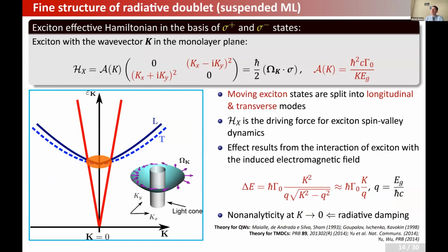So in a more formal way, you can derive this kind of expression for the effective exciton Hamiltonian in the basis of sigma plus and sigma minus polarized states. And these off-diagonal terms, you see, they contain the second angular harmonic of the wave vector. And because they flip the polarization, you need to change the polarization from sigma plus to sigma minus, so you need to introduce or to remove the momentum component being 2. So these are second angular harmonics. And this Hamiltonian looks like an effective magnetic field acting on the exciton pseudospin. And the coefficient here actually has a very simple form. This coefficient depends on the exciton radiative decay rate gamma naught.